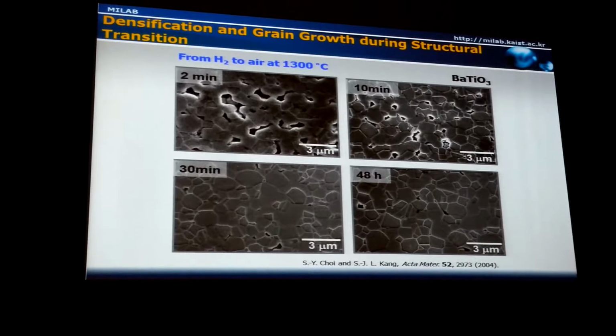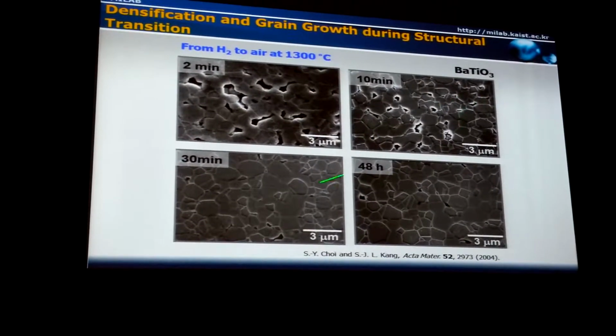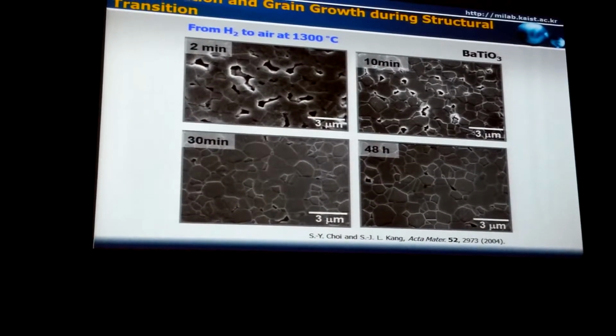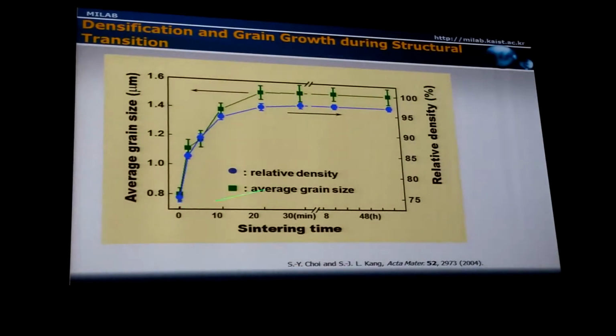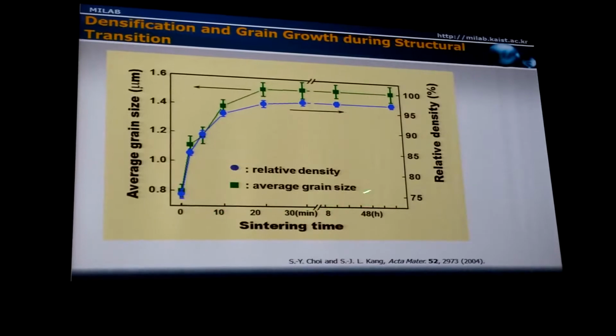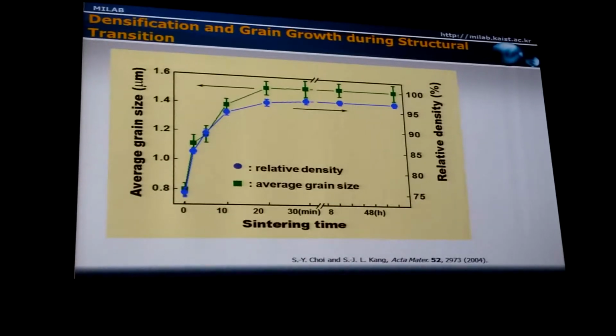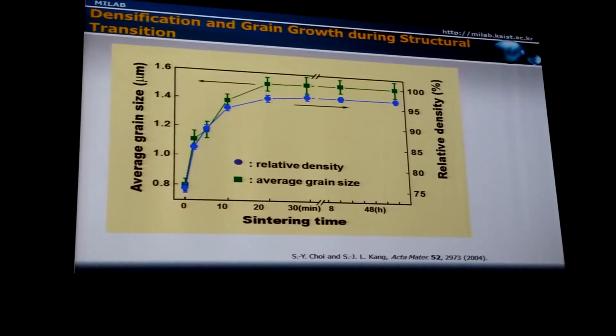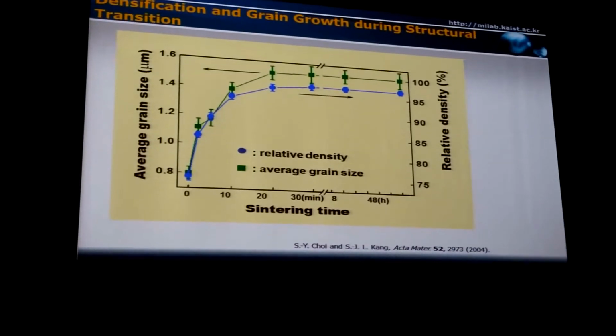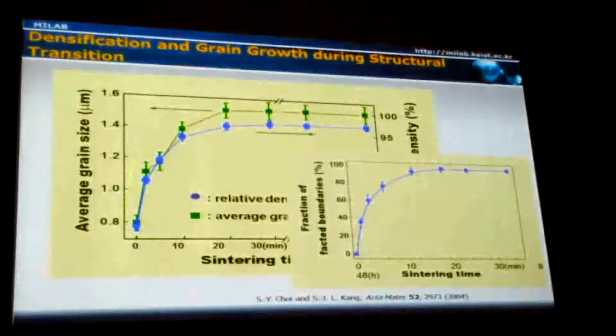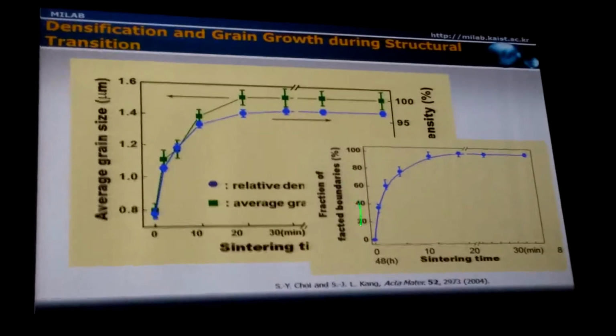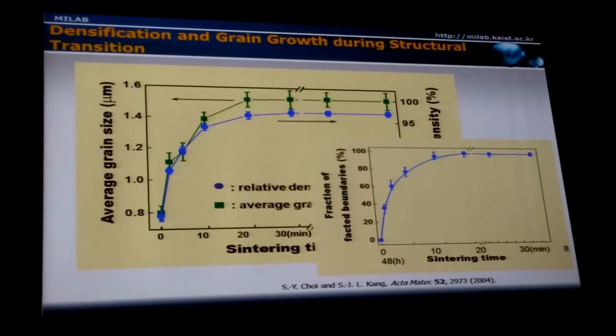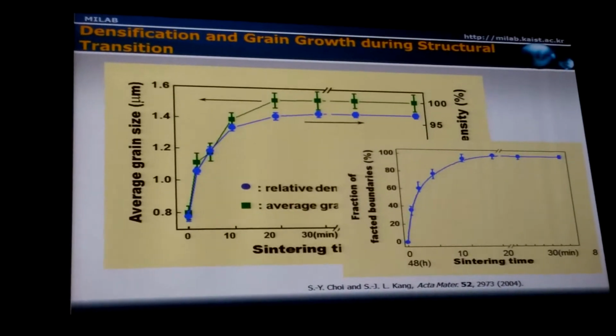As you can see here, densification occurred a little bit, and then grain growth occurred. But after 30 minutes, there was essentially no change in microstructure. So we quantitatively measured the average grain size and the relative density as a function of the annealing time in air. Grain growth occurred a little bit, and densification occurred also. But after 30 minutes, there was no change in grain size and density. When you compare this measured grain size and density with the fraction of faceted boundaries, we can easily notice that when the boundary is fully faceted, there is no grain growth and no densification.